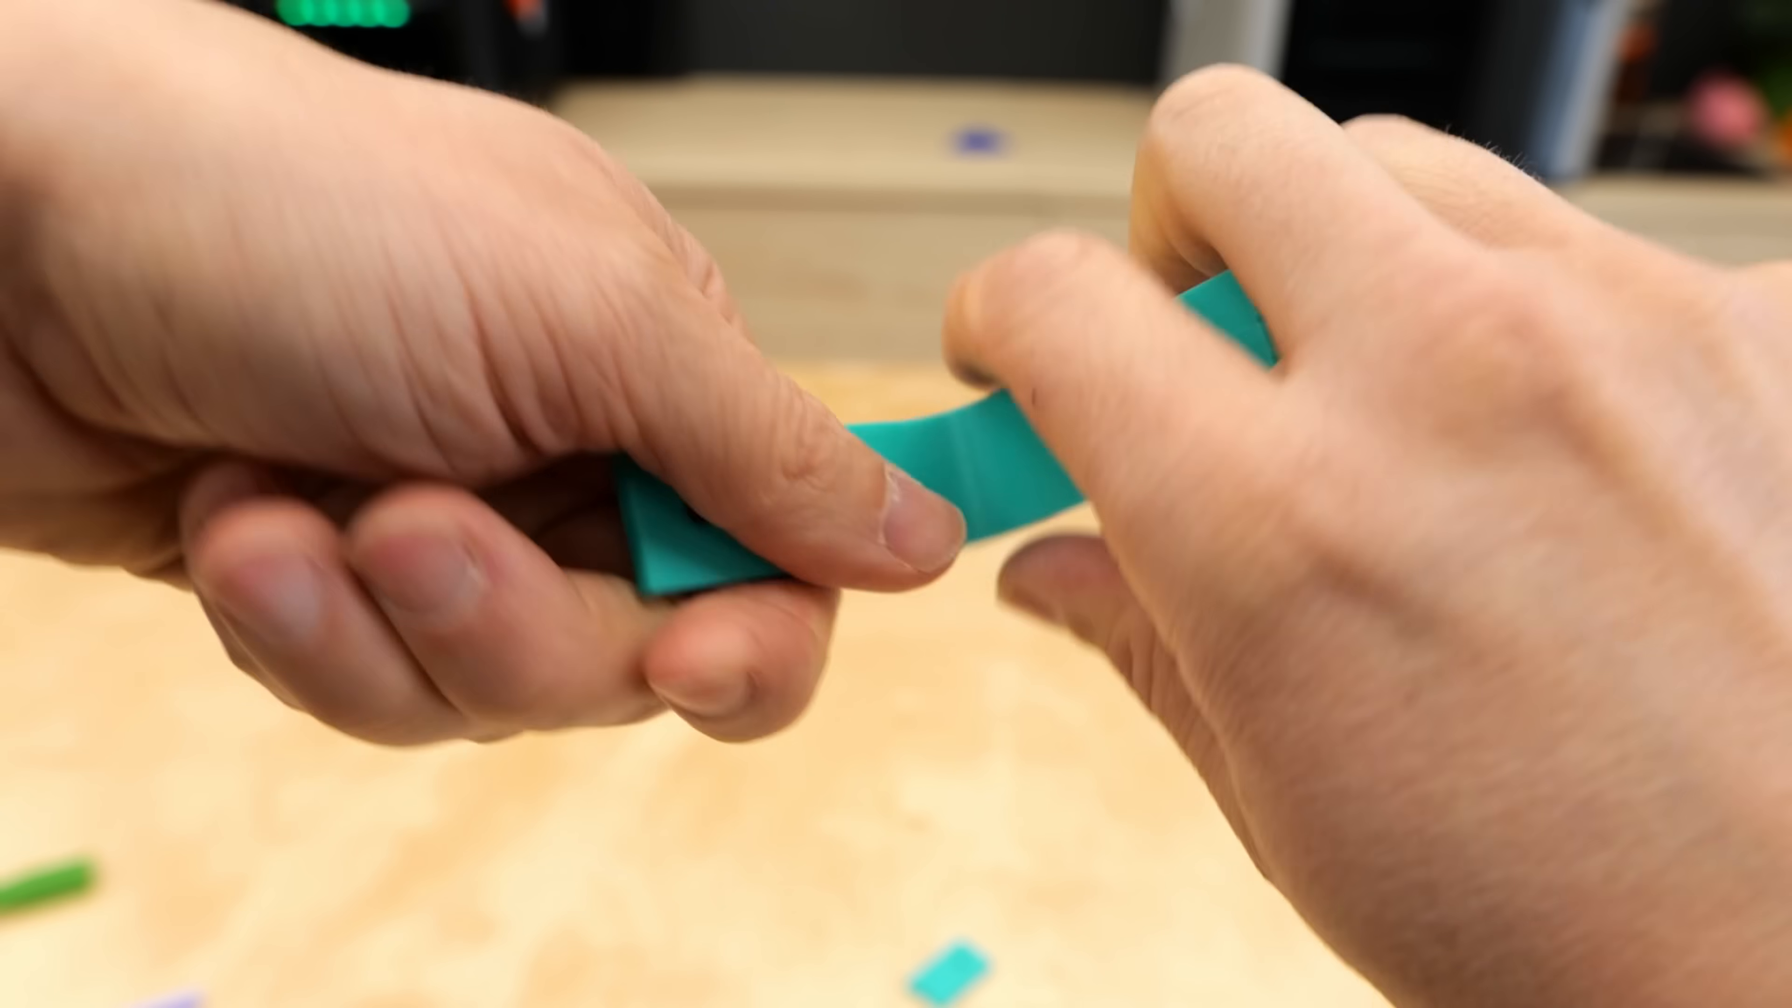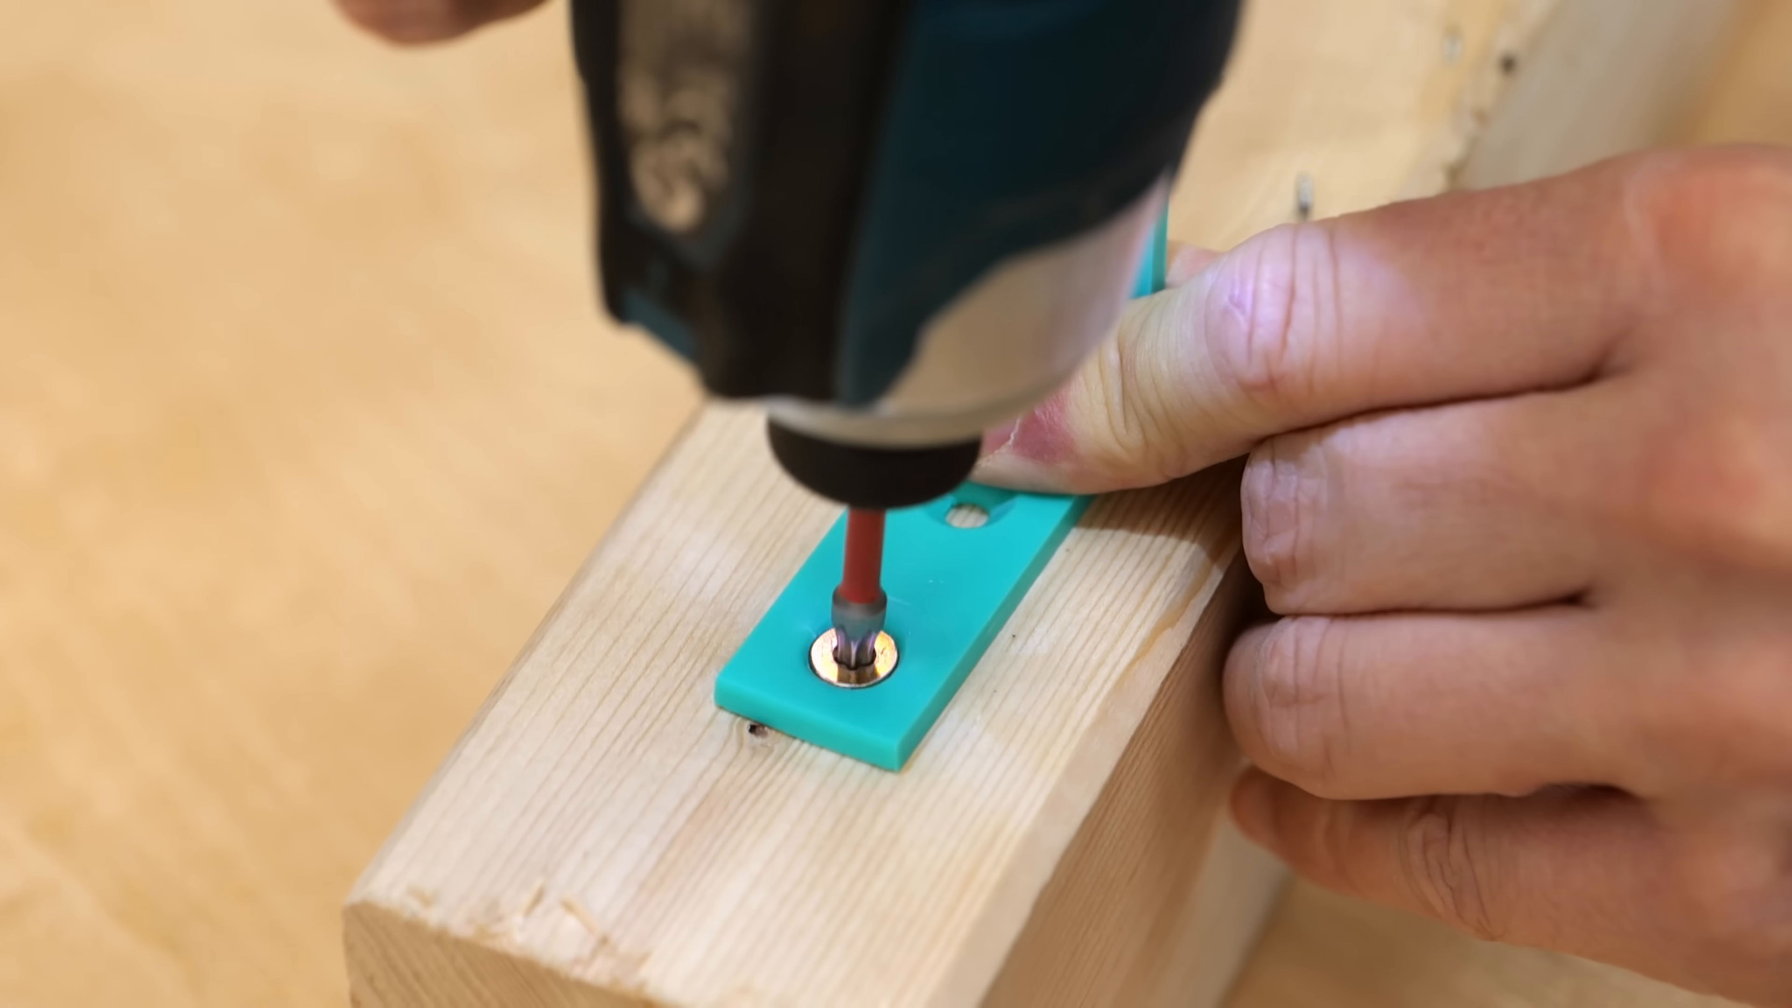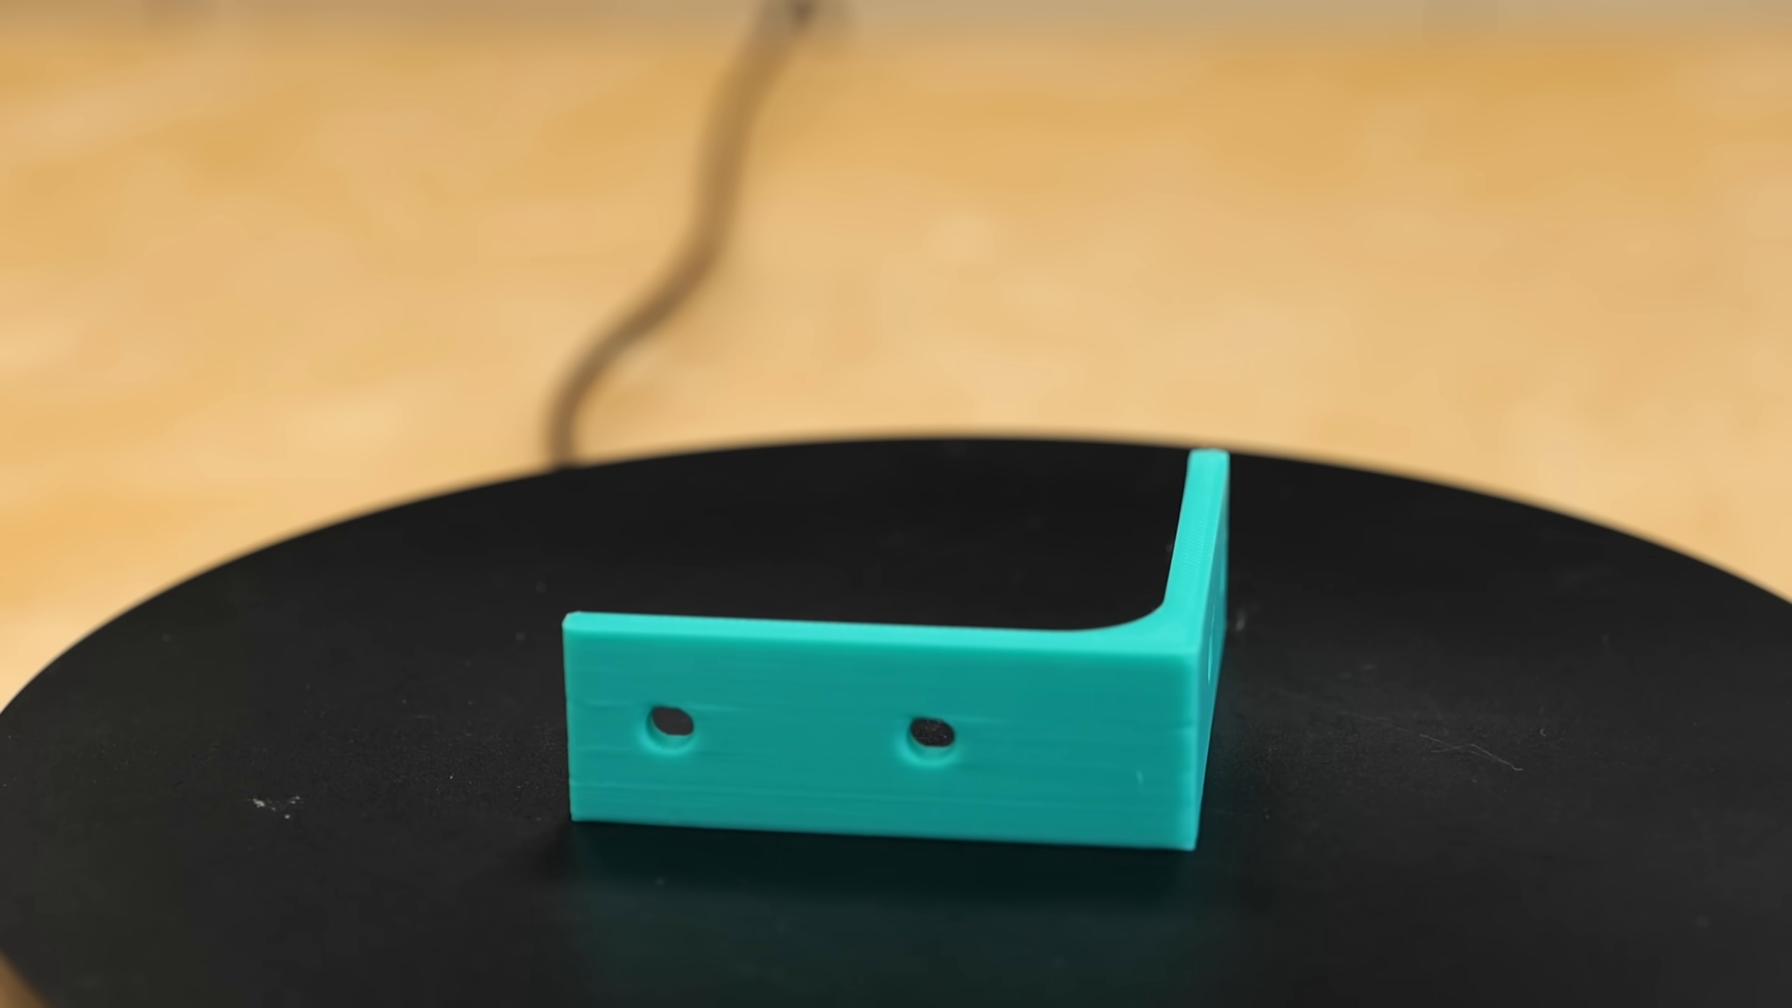But this can also lead to other problems with the bracket. Especially with warp-prone materials, printing on the side can cause the ends to lift and lead to print issues. And if you replace the standard through holes with countersunk holes, we face another problem. When installing a regular wood screw into one of these holes, the tightening force will try to split the part. The layer lines again go directly through that hole, creating a weak point, which wouldn't have been the case on at least one of the sides when the bracket was printed flat. So you see, even with such a simple part, the clearly strongest printing direction has still its own set of problems.